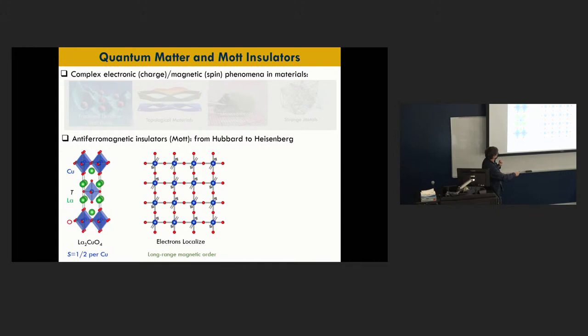So out of all of this complicated theoretical technology emerges a very simple model that was actually invented before we knew about the Hubbard model, which is called the Heisenberg model. The Heisenberg model says that if you have two spins that are nearest neighbors on the lattice, there is a certain cost in energy associated with their dot product. We call this the exchange interaction. It turns out the exchange interaction can be derived as a function of the Hubbard parameters, t and U. It's t squared over U. And for reasons I don't have time to explain, but that involve the ligands that also participate in this phenomenon, this exchange interaction can be negative, and if you minimize the energy, you get two spins aligned. Or it can be positive, and you have antiferromagnetic interactions.